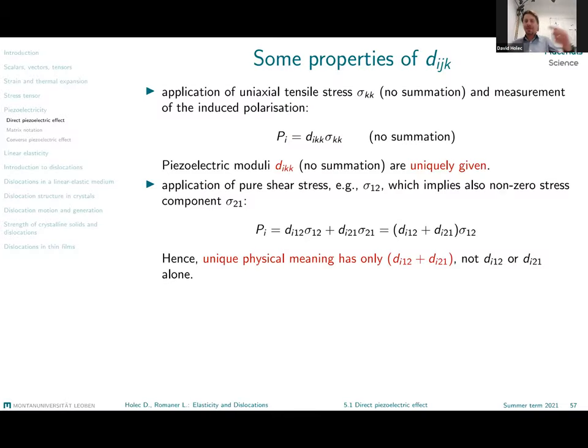Well of course you can then start applying instead of this purely compressive or tensile stresses, you can start applying also the shear stresses, why not. The problem is that from the definition of the stress tensor, from the fact that the stress tensor is symmetrical, we will not be able to distinguish between components di12 and di21 again because these two stress components are identical. And all what we can measure is that we apply a certain shear stress σ12 and this will be always related to a sum of these two components. So in order to resolve this ambiguity we define also the piezoelectric tensor as symmetrical with respect to the exchange of the second two indices.